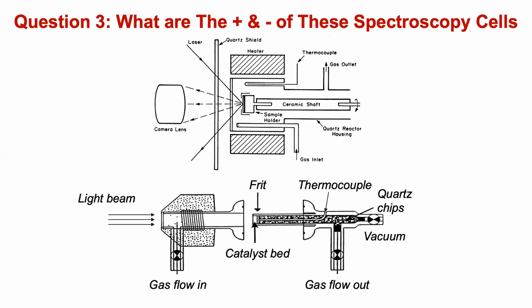Hence, you will have also effects. When this cell has been compared with lab activities, the bottom one, you can note that also the temperature is not correct. The temperature is off because you are heating the sample much more. It can be off by 10, 20 degrees C. And that is something you have to be careful about in these designs: what is the temperature?